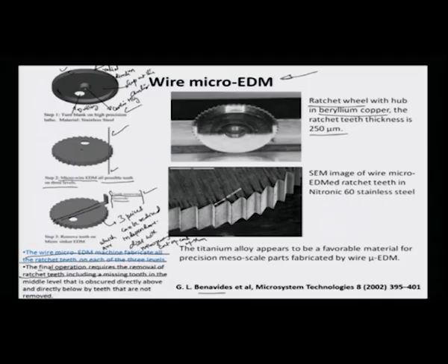So, this right here shows a detailed view, a SEM image of the wire micro EDM'd ratchet teeth structure, and this is in nitronic 60 stainless steel, and they have also done it for titanium alloys, and they have seen that the process is quite favorable for machining titanium alloys also by micro wire EDM. So, this is a very highly capable process now for doing these micro features and structures. You can imagine the ratchet teeth thickness of 250 microns this one section here is only 250 micrometer thick, and there are 3 such sections and different levels of this particular mechanism.